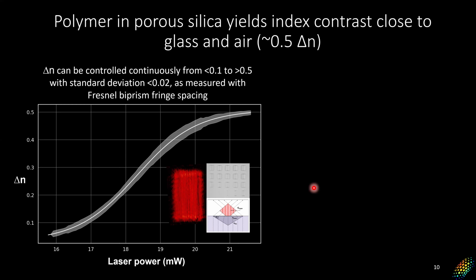And so this polymer in porous silica scaffold is the most mature process. This gives us a maximum index contrast comparable to that between glass and air. We measure this by making triangular prism structures called Fresnel biprisms, which you can then send a collimated laser through. This tilts the two beams by an angle that's defined purely by the refractive index difference. And then you get an interference pattern where the fringe spacing tells you what that index contrast is. From this, we've measured continuous control of the effective refractive index from less than about 0.1 up to a little above 0.5. And in absolute terms, from about 1.05 to about 1.55.